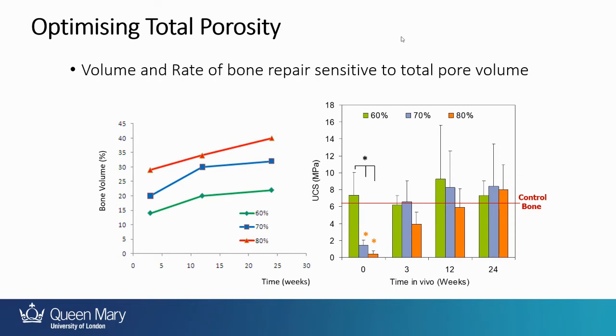One of the things I did as a PhD student is look at the fact a material which had such a wide variety of porosities, I could take different samples, characterize them, and split them into 60%, 70%, and 80% groups, and then do the analysis on how bone grew into those different groups, and found quite remarkable variation in the amount of bone volume and the rate of bone regeneration related to the porosity.